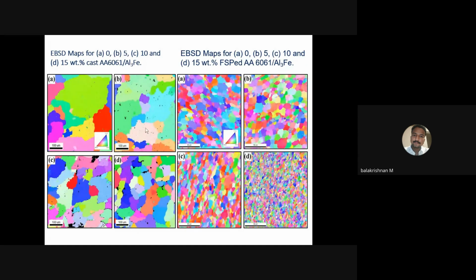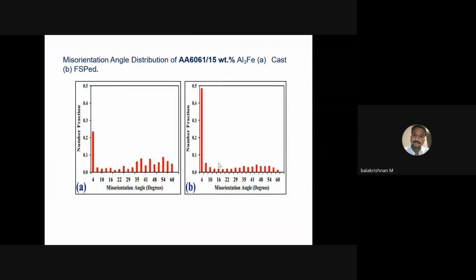Here we have friction stir processing, which acts as a deforming technique used to deform the crystal structure. After friction stir processing, we can observe fine refinement of the grain. At 15 weight percentage, the grain refinement happened highly. So with this, we confirm that the tensile strength of the material is definitely going to improve.